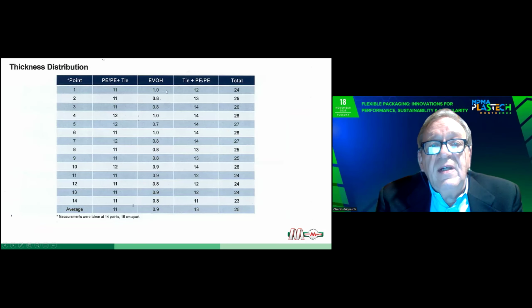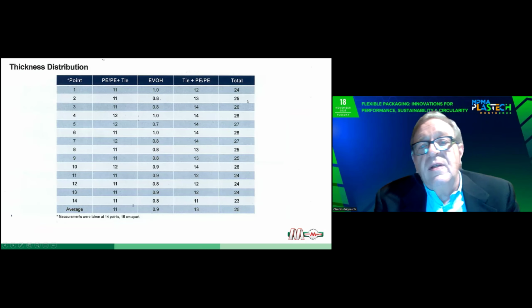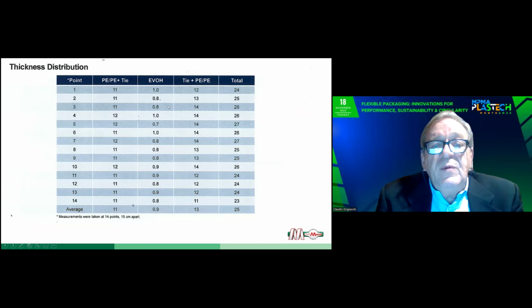And this was the result. As you can see, film thickness distribution on a 25 micron total structure, we were constantly running up to a maximum of 1 micron of EVOH.